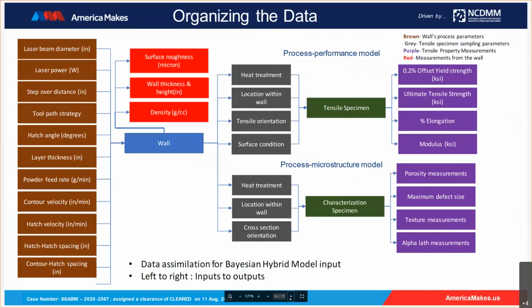Yes, taking a step back from a microstructure standpoint, you again take the component, you heat treat it, sample material from different locations within the wall, and that can undergo characterization, and you can once again get measurements of porosity, microstructure measurements such as alpha lath measurements, etc. So you structure all of this and create a matrix with inputs and outputs clearly distinguished. Next slide, please.